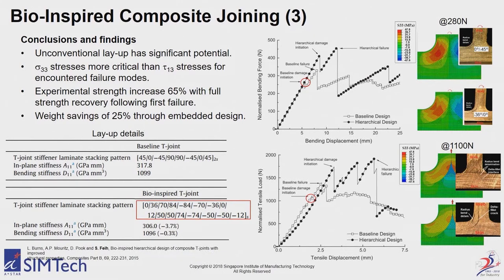But more importantly, actually, for an adhesive joint, once first failure happens, we can actually completely recover the strength, and the second failure peak is going to have higher strength than the first one. And that means that if you have an accidental overload and you introduce cracking, there's no danger of the structure failing catastrophically, because we know that the next peak is going to be higher than the first. And that is a very important thing for adhesive joining, to actually have this kind of hierarchical failure mechanism where you can recover strength after first failure occurs. And that is not something that we typically see with composite joints that are just connected with an adhesive layer.